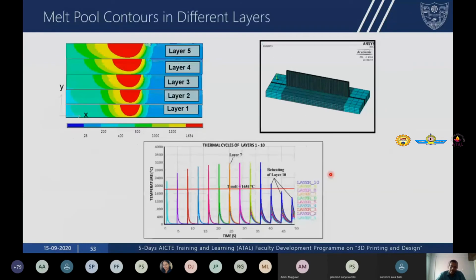Here, I'm showing you the simulation of a thin wall geometry of Ti64, and you can see the evolution of the melt pool geometry as the number of layers increases. You can clearly see that as the number of layers increases, the size of the melt pool increases. This is because when you're depositing the first layer, you have the substrate beneath the layer, which is at room temperature generally, which acts as a heat sink and removes the heat. But as you are depositing subsequent layers, the effect of the substrate decreases, and therefore the size of the melt pool increases as you increase the number of layers.